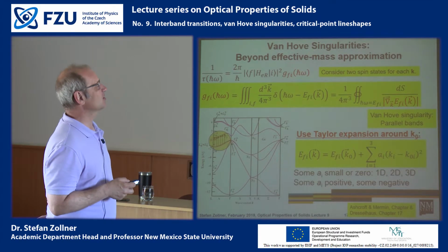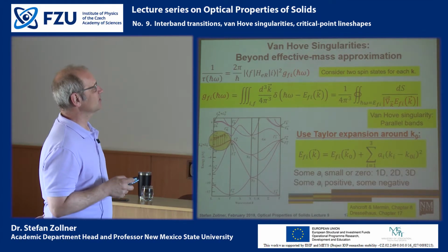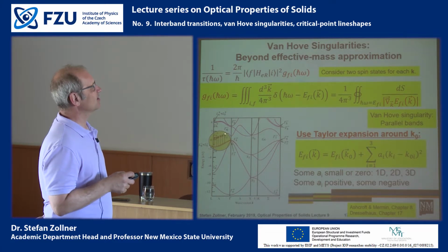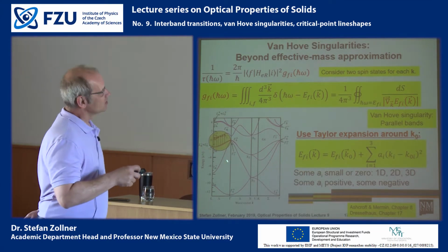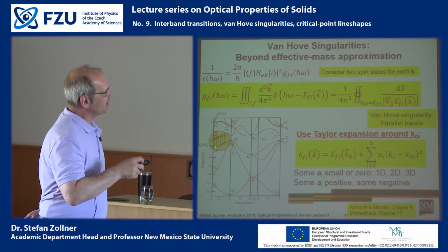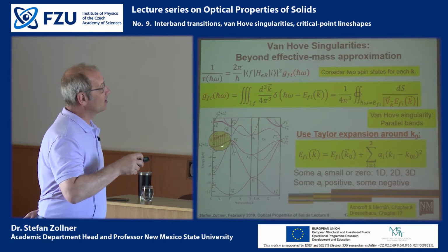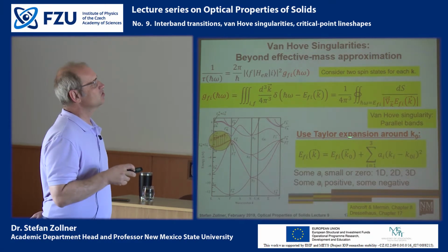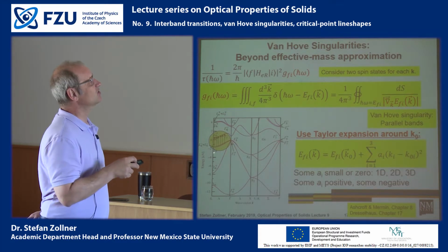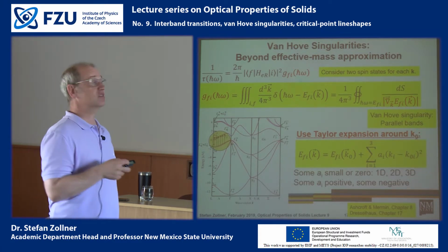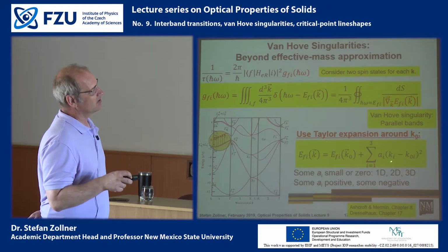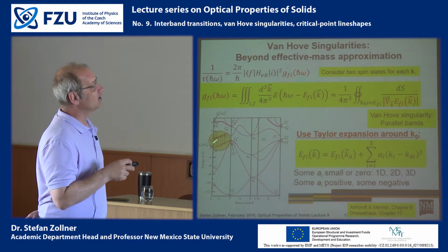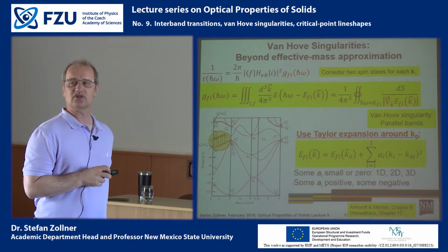That is used in the nomenclature that I will explain on the next slide. So let's look at this at the 111 region in the Brillouin zone. As the k vector varies along 111, there is no change in the energy difference between these two bands because these two bands are parallel in the 111 direction. Therefore, this coefficient A along the 111 direction is 0.